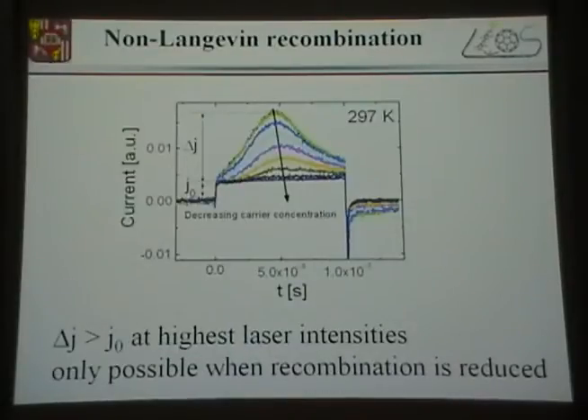So that's the problem, and we've seen that some solar cells have a non-Langevin type recombination, that is reduced recombination compared to the Langevin type, and the best way to see it is simply from the CELIV method. This is when you see that delta J is much larger than J0, at the highest laser intensities.